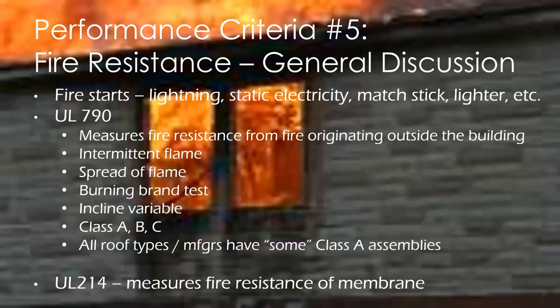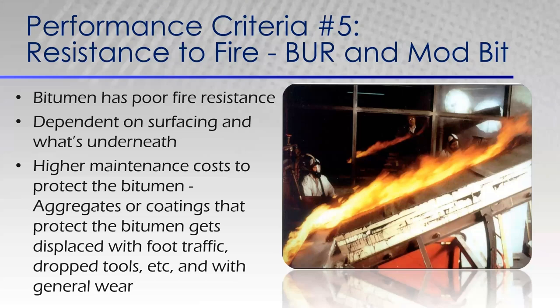When we look at UL 214, UL 214 measures the resistance of the membrane only, after the ignition source has been removed. So we're looking at the membrane itself and its performance once the ignition source has been removed. With UV exposure over time, what you see with built-up roofs and modifieds is that because it's a petroleum-based product, it will burn. You have the surfacing on top of your granular cap and your coatings to protect it, but it requires more maintenance to keep it covered. As those oils leach out, it provides an opportunity for fire. So they don't have a great resistance to fire.